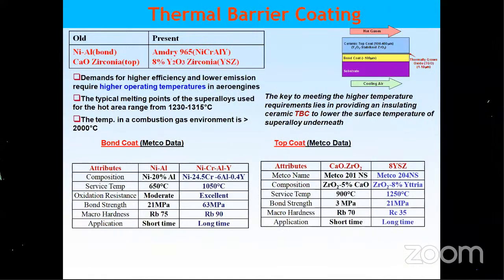Now, during combustion, the temperatures are reaching, as I showed earlier, 3000 K. To arrest the heat transfer to the chamber material, we have to give a ceramic coating, which I was mentioning. Ceramics, especially zirconia, have a good property: poor conductivity of one watt per meter Kelvin or less. So this will eventually break the heat transfer to the chamber material.